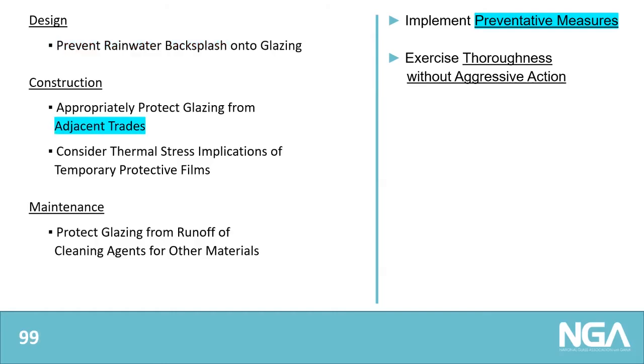From the standpoint of construction, we want to protect the glazing from adjacent trades, and sometimes we would use a protective film in that process. When we're doing so, we want that film to be protective, of course, but we don't want it to be any thicker or darker than necessary, because the film could have the effect of amplifying the thermal load on the glass, and in a worst case scenario, breaking the glass. From a maintenance standpoint, we want to be sensitive to the cleaning agents used on adjacent elements of the building skin. Particularly in residential construction, brick wash can be detrimental to glazing systems, so we want to be sensitive to that possibility.